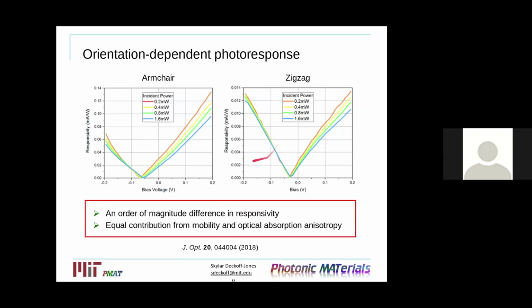And from this, we're able to now compare the photo response of the photodetectors along the armchair and zigzag direction. If you look at the scale of the responsivity, we actually have just about an order of magnitude improvement in the responsivity of devices oriented along the armchair direction, which is quite nice. And if you look at the theory of the physical properties of black phosphorus, this actually ends up making quite a bit of sense when you account for the differences in both the mobility and the optical absorption anisotropy in the black phosphorus.